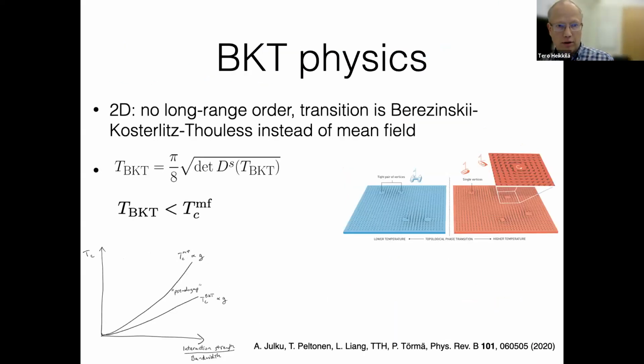In this case, the only thing you need to consider beyond mean field is that if you have a 2D superconductor, the transition to the superconducting state is not described by mean field theory, but by the Berezinskii-Kosterlitz-Thouless transition, where the vortices become trapped below this BKT temperature. In practice, this means that there may be a phase between the BKT temperature and the mean field TC where there is a gap but no supercurrent, no real zero resistance. And it is actually this BKT temperature that has been measured in the experiments.